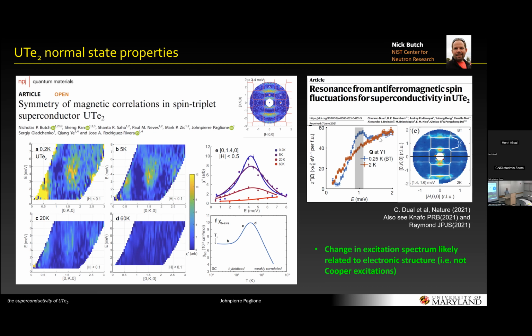One way, you know, the standard way, is to think of this as an antiferromagnetic Q vector, so in sort of incipient order. My colleague Nick and our group have interpreted it a slightly different way, in that this is probably arising from some interband transitions to do with the band structure. But that's also occurred in debate. So the interesting thing that was observed by Pengcheng Dai's group was that in the superconducting state, at this Q vector, there's a resonance. And that's been seen in other superconductors, resonance at some Q vector.